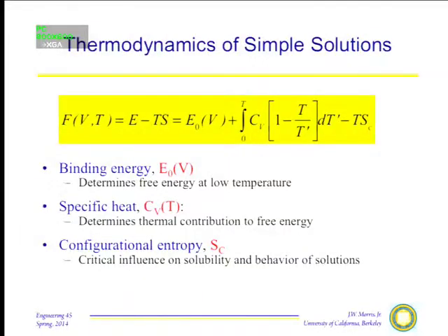Okay, let's get started. What we want to do today is phase diagrams and how we use phase diagrams to design processes, gain insight into how materials behave, and so on. Recall our free energy of a multi-component system that can form a solid solution is really controlled by three terms: the energy of the solution at absolute zero, the specific heat, and finally the configurational entropy, which is specific to a solution and arises from the fact that there are many, many different ways to arrange the atoms in a solution, each one of which contributes to the entropy.